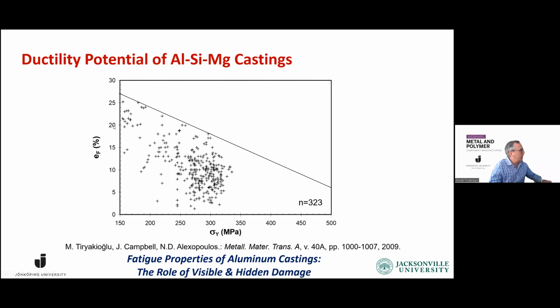So when we look at the trend of the maximum points, we can write an equation and we call it the ductility potential. A simple best fit formula is 36 minus 0.064 times yield strength, where yield strength is in megapascal. So we can use this as a good point to estimate the potential ductility of our castings based on the yield strength.